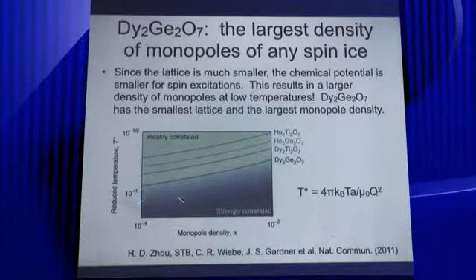So I'm going to shift my attention to dysprosium germanate, and one of the reasons why is shown nicely in this figure that we published in this paper recently. This is looking at a reduced temperature scale versus monopole density, right? And we reduced the temperature scale by a characteristic monopole energy. You'll notice that at any fixed temperature here, dysprosium germanate will have the highest concentration of monopoles. Actually, it's an order of magnitude different from dysprosium titanate, right? So if you're really looking for monopoles, you want to look at a system like dysprosium germanate, which sticks out like a sore thumb. So that's why we concentrate on this compound and did a rigorous analysis of the specific heat to learn something about what's going on with the monopoles.